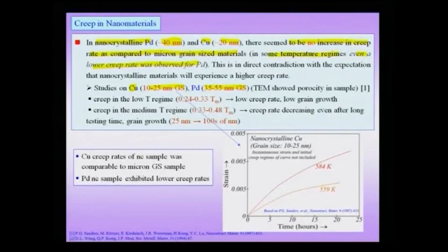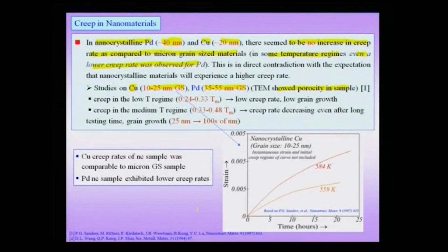And TEM in these structures showed there is porosity in the sample. That means there was some damage, and the question of course arises whether this damage accumulated during the testing time, or was an effect of the prior porosity in the sample. So, this is an important question. I do not think the authors investigated that part.